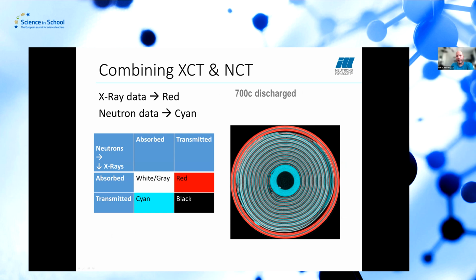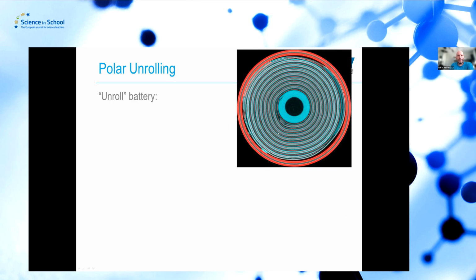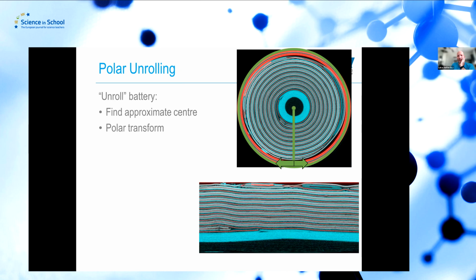And you get highly neutron absorbing structures here, for instance, the lithium containing cathode material that is in a discharge state. And what you can then do in order to get profiles across the battery and to show the different charging states is that you can virtually unroll the battery. You can do a polar transform and then put the different layers in a polar diagram, and you can then see the different layers and the local fluctuations of the layers. And you can do that, of course,